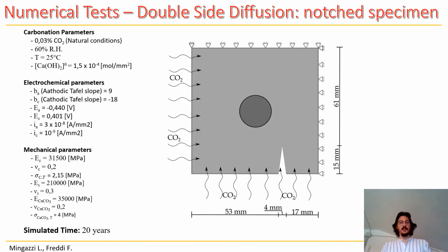For the second test, we considered the same geometry, initial conditions, and boundary conditions as the previous experiment. However, we introduced a notch on the bottom side to evaluate the changes in the carbonation profiles as well as in the crack patterns that can be seen if pre-existing cracks or openings are present in concrete.